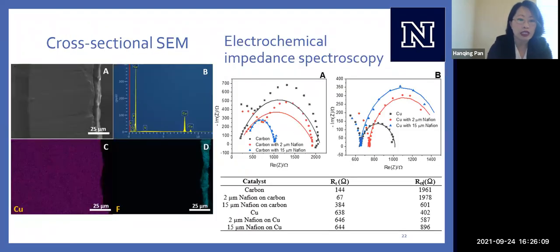So we can confirm this by looking at our sample under an electron microscope. Instead of looking at it from a top-down view from before, we can look at it from the side, which is a cross-sectional view. And so elemental composition analysis is helping us to verify this really thick piece here is our copper metal substrate. And on top of that is our Nafion membrane overlayer.